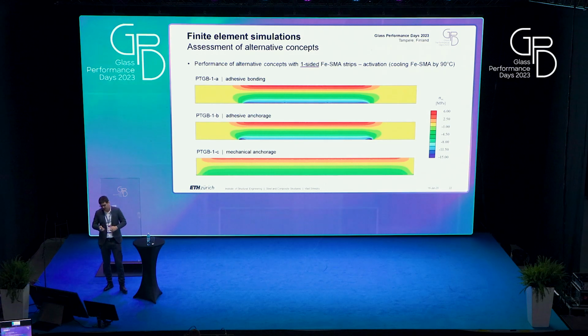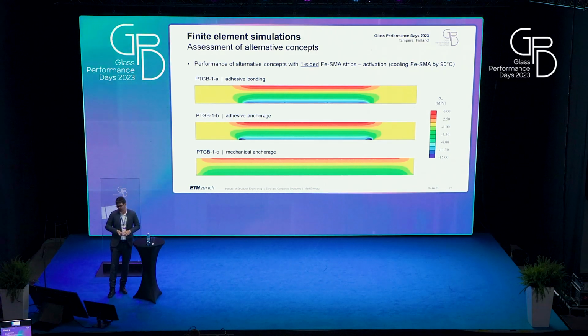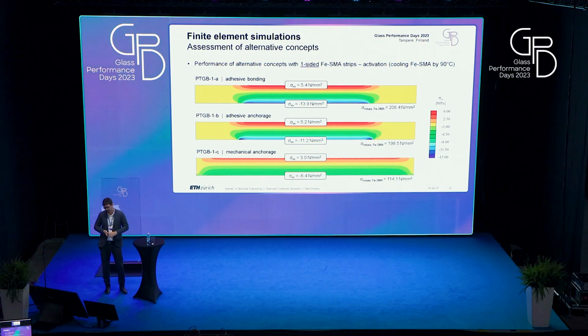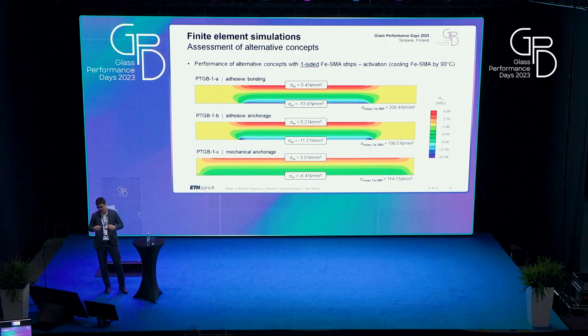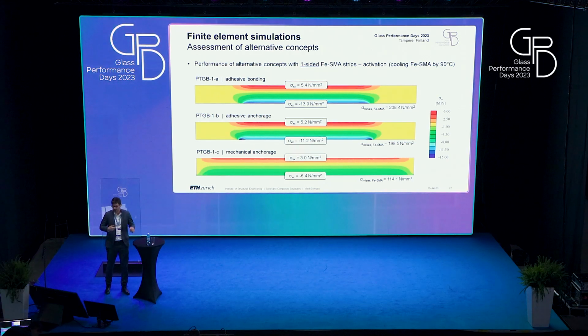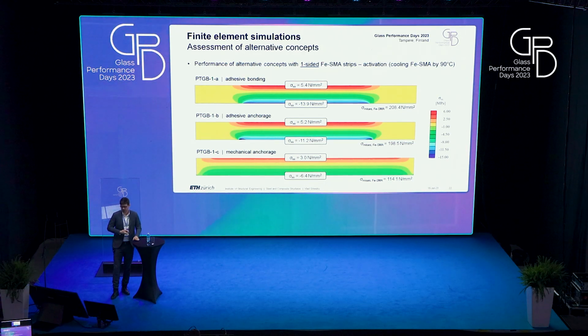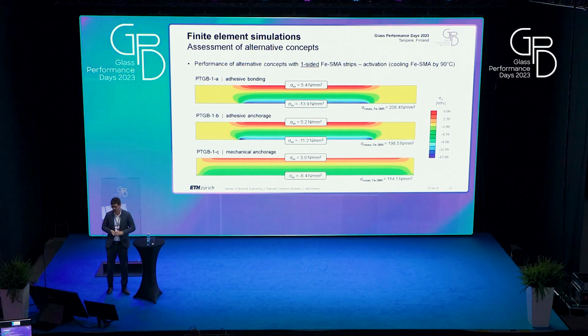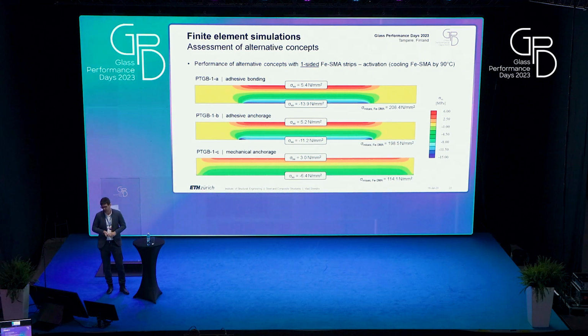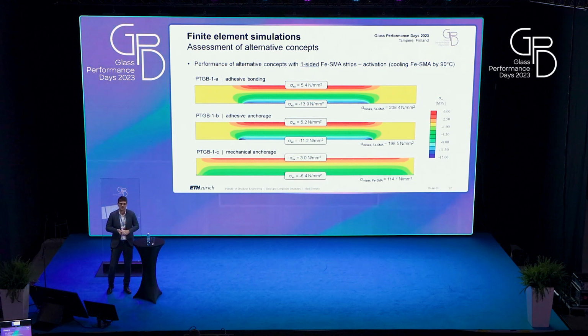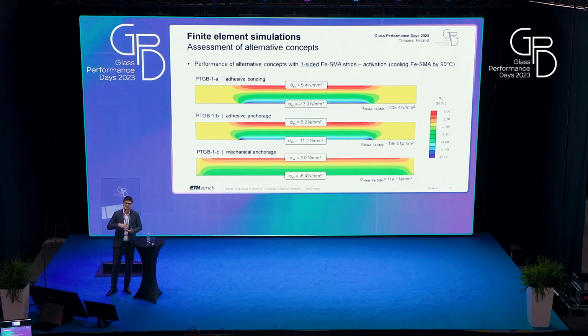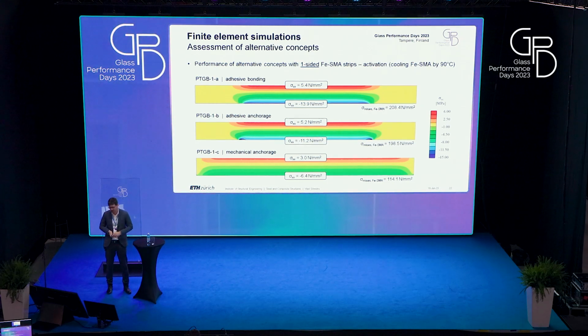For the concepts with one-sided strips, the trend in terms of values was similar, so we could pre-stress it the most if we have adhesive bonding along the whole length. And what we observed on the bottom edge, we were able to reach a higher pre-stress value if we have the strip only on one side. But as I said before, this works if you have a beam in a glass roof or something like that, where you don't expect tension along both edges.